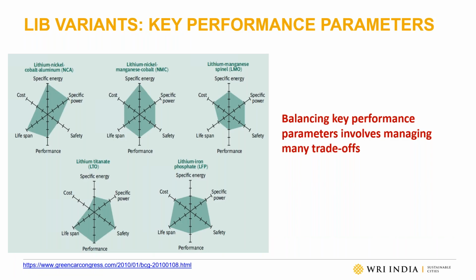In this slide, I have summarized the key performance parameters of different lithium-ion variants. In the case of lithium iron phosphate, you can see that it can give very high safety, but one needs to compromise on the specific energy and performance. So it's very important to understand the application and limitation of the battery, and that will help in choosing the best chemistry for a selected application. Making a good battery is a big challenge. It requires balancing key performance parameters and managing many trade-offs.